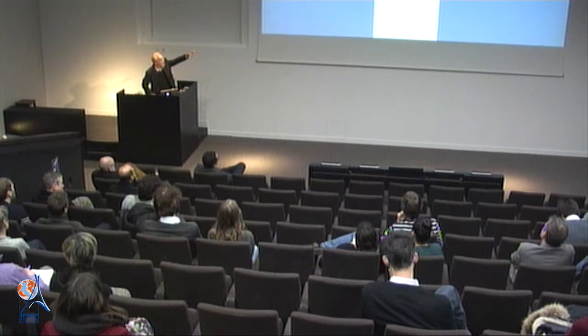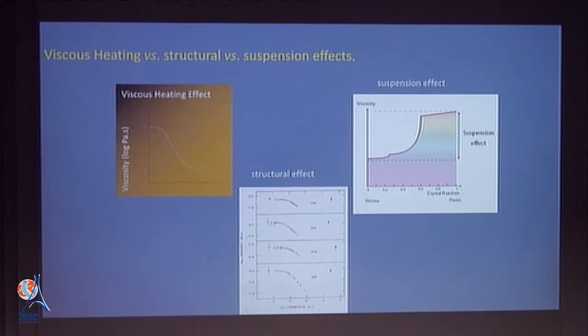And then, of course, and as a general rule, we have the suspension effects. We have the fact that we have up to tens of percent of porosity in terms of bubbles, and we have up to tens of percent of crystallinity, which are certainly inviscid particles, which will complicate the rheology of this description. So we try to pick apart these effects.